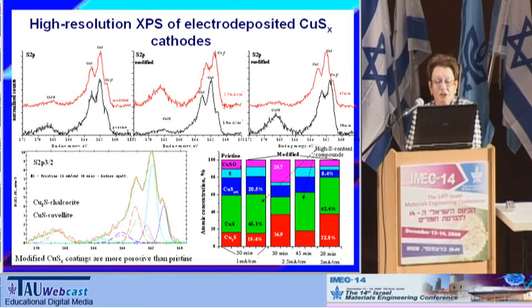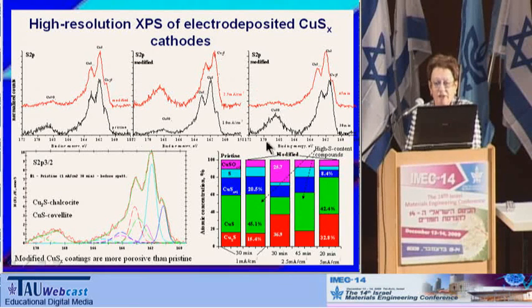Analysis of the high-resolution XPS spectra of the electrodeposited copper sulfide materials revealed that modified samples are enriched in high sulfur content compounds like covellite. However, the high deposition rate films contain large amounts of sulfur-poor chalcocite. Increase of the deposition time restored the initial content of the covellite, as you can see from this spectra and from the analysis shown at the bottom, and also reduced the surface oxidation.